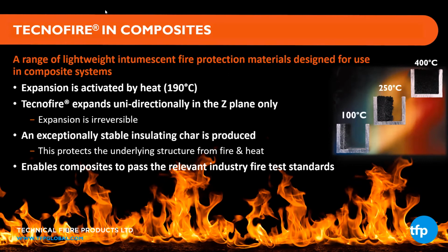They expand or intumesce in the Z direction to form a stable, insulating carbonaceous char that protects the backing laminate from heat and oxygen getting through to it, and any potential liberated fuel gases from escaping. And these products have been established in composites for well over 20 years. Next slide, please.